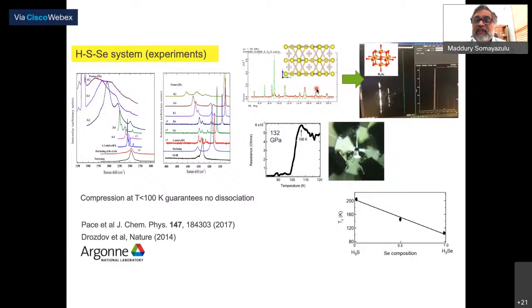We can also do resistance measurements. I'll go into that more in detail later. But what it shows here quite simply is that as you replace sulfur with selenium, your transition temperatures drop. And the drop in transition temperatures follows the systematics, which can be used by the theoretical people to actually understand what the modulation of selenium, sulfur or selenium is with the whole hydrogen clathrate cage and how it stabilizes it.